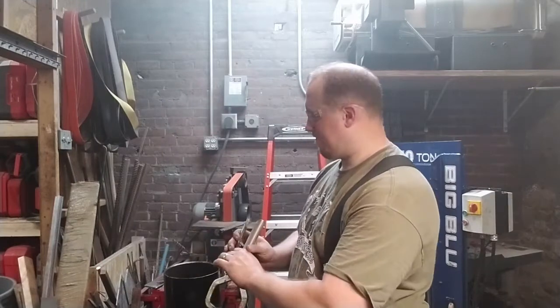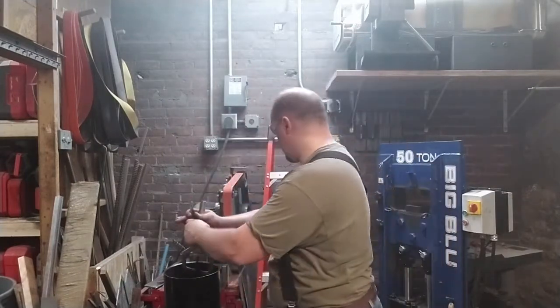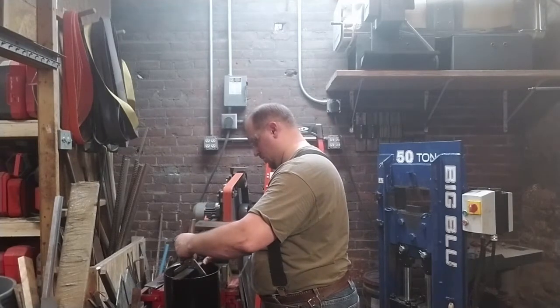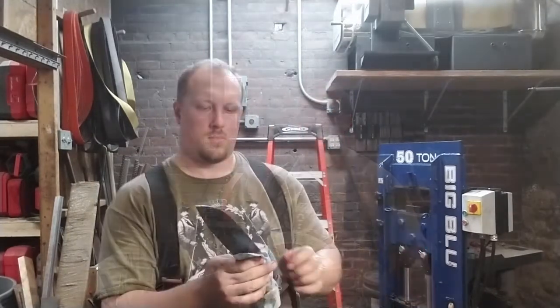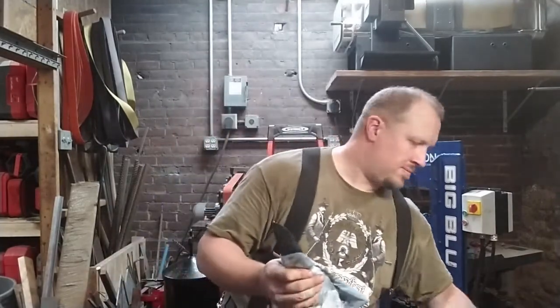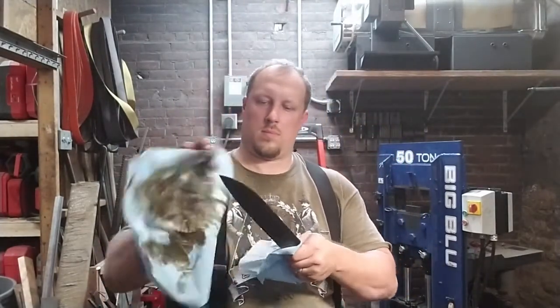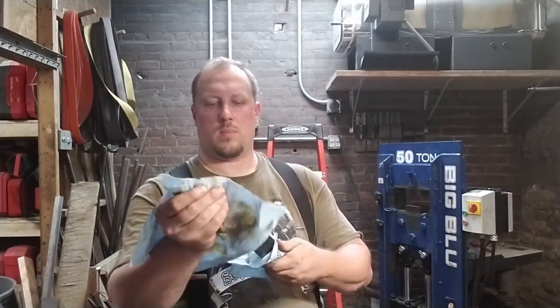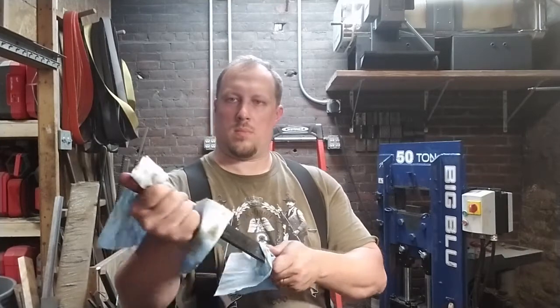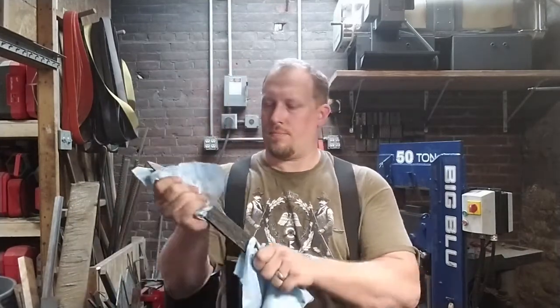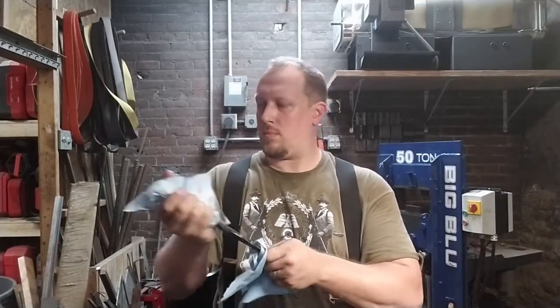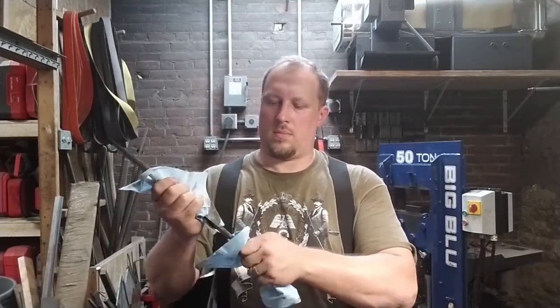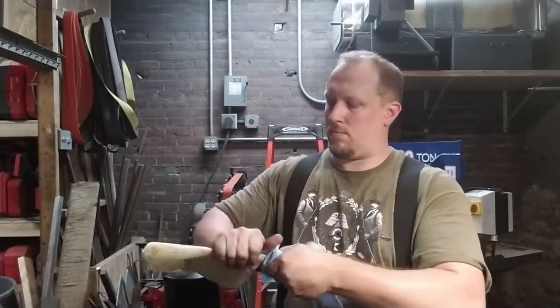Now, every hard blade needs to be tempered. The stress needs to be relieved. We did a good job of getting a lot of the stresses out of the blade during the normalization process, but hardening causes its own. And it's rare, but it has happened that a blade that's left hardened, just sat out in the air, will snap and destroy itself because of the internal stresses that the hardening process has created. So you always want to temper, at least do a preliminary tempering right after hardening as soon as possible.